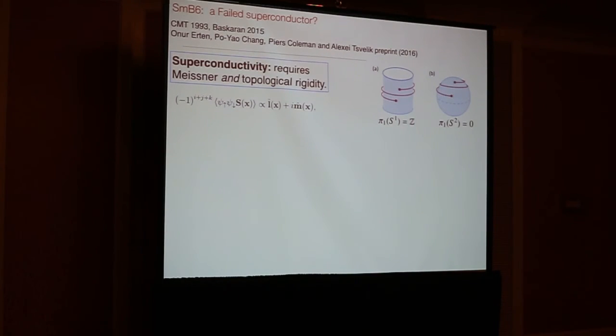Its spin component is analogous to a spin-half ferromagnet, and as a result it can be isotropic inside a cubic environment. And this then means that its manifold is the manifold of the group SO(3), which doesn't allow Z vortices, doesn't allow the quantization of circulation. And so even if this doesn't apply to samarium hexaboride, it's an interesting notion to explore.